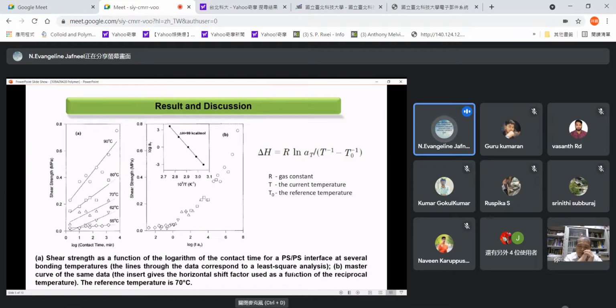Now to the results and discussion. Here are the data for the shear strength of the asymmetric and symmetric blends. In the slide, we can see two graphs. The first graph represents the shear strength developed at the PS-PS interface. The plot is between log contact time and shear strength. In that, we can see that as the temperature increases from 55 degrees Celsius to 90 degrees Celsius, the shear strength also increases.